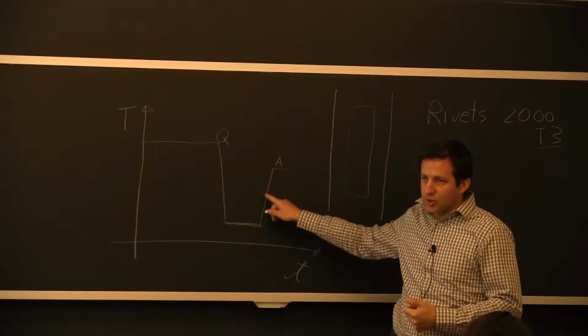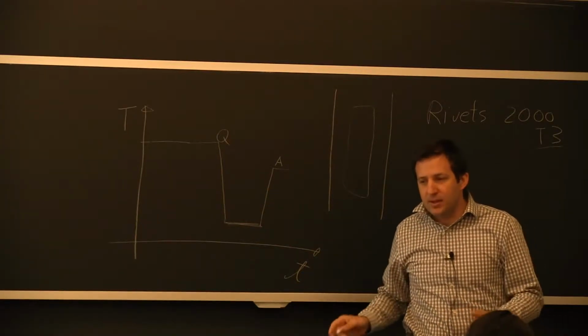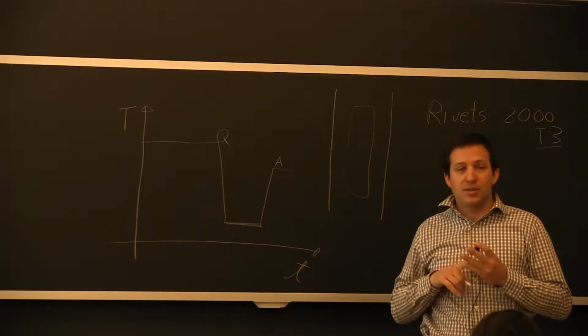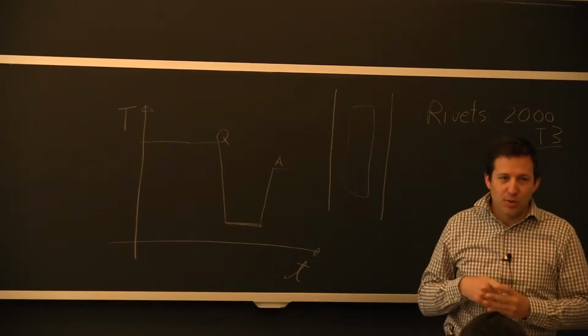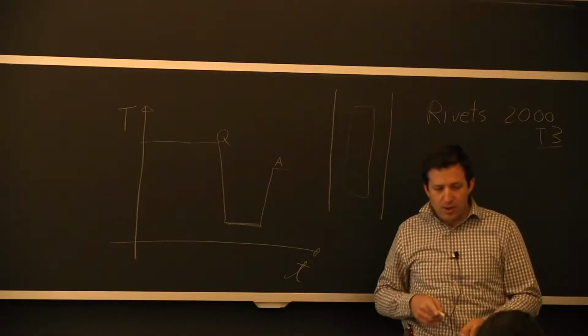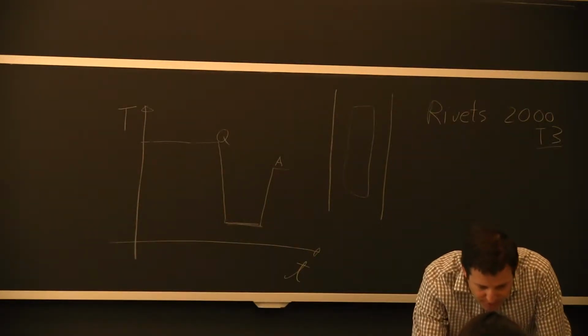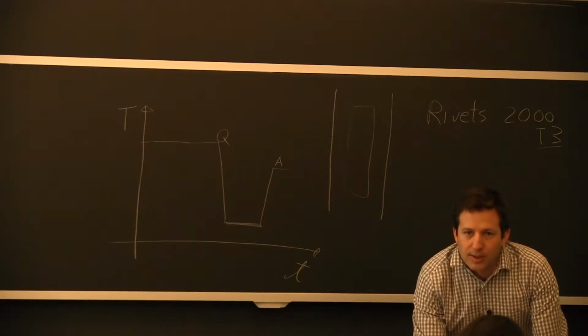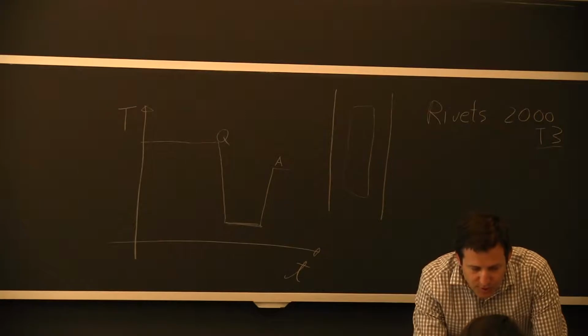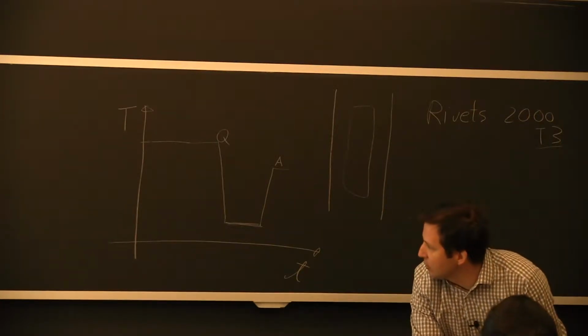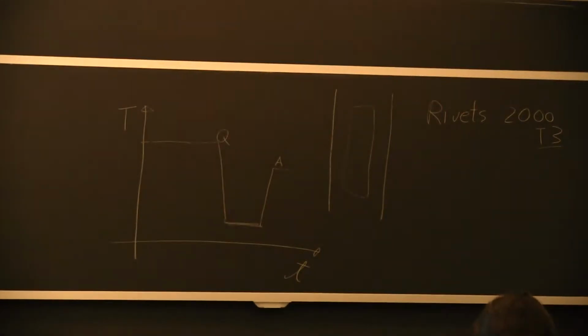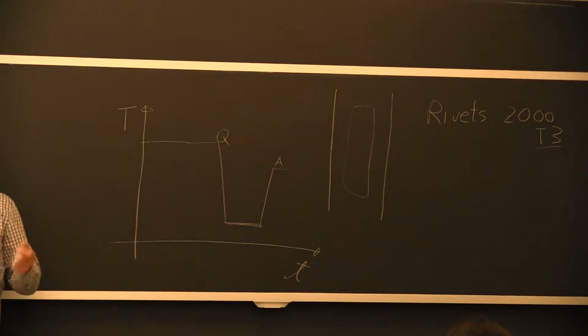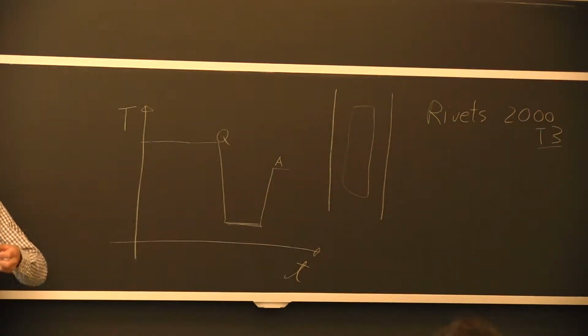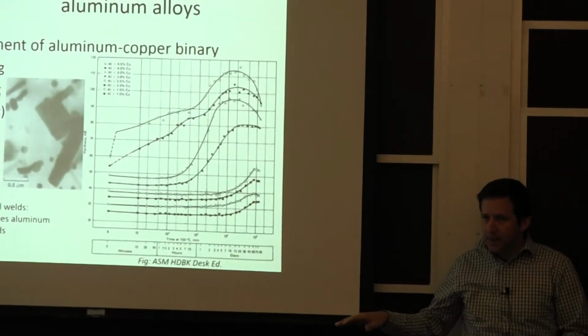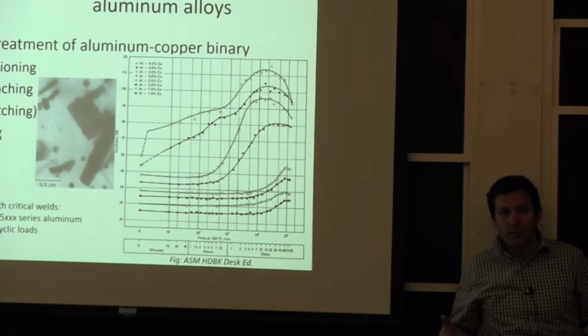When you start aging and you start forming the precipitates, there are, depending on the alloy series, approximately 4 different kinds of precipitates you can form. The first one to form at low temperature are so small, and I'm showing some of them here. You're looking at less than 100 nanometer little formations of a different composition in the aluminum alloy. So this scale here is 500 nanometers. A lot of them will be coherent, which means that you have a different composition, but your lattice, your crystal is still continuous. It's deformed, but it's continuous.